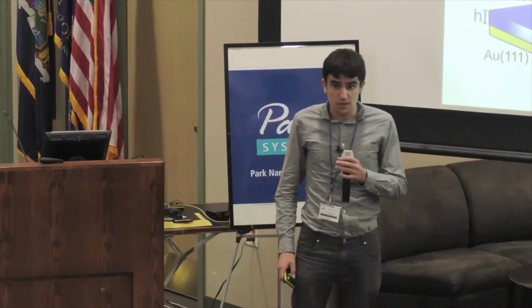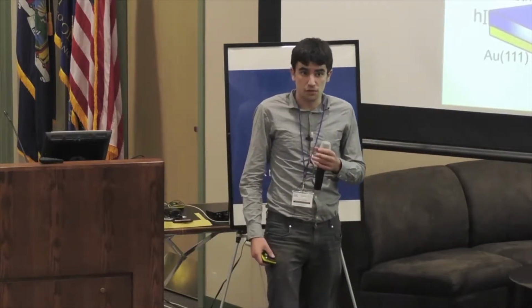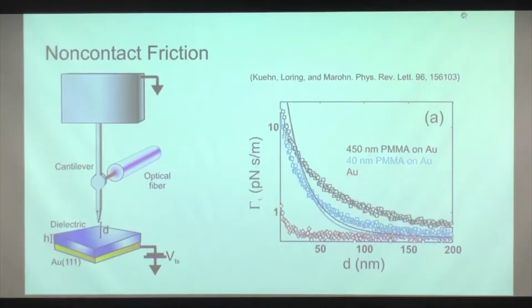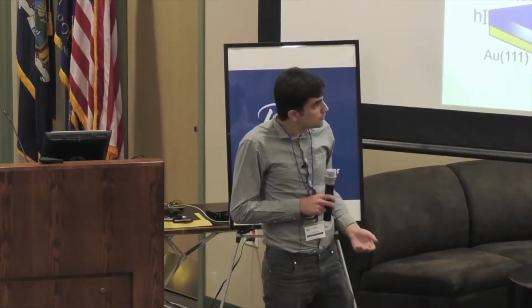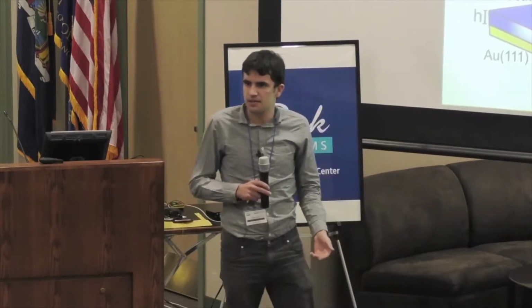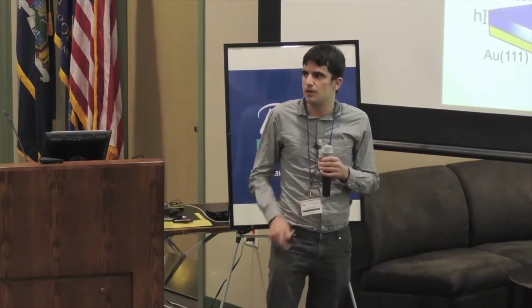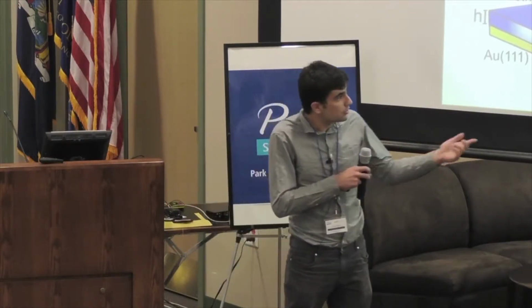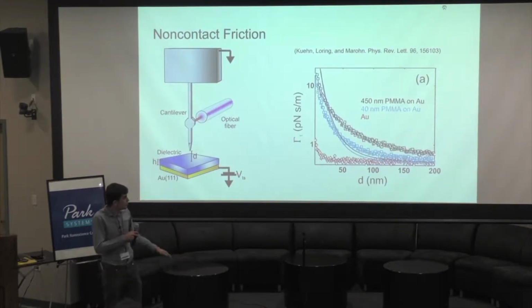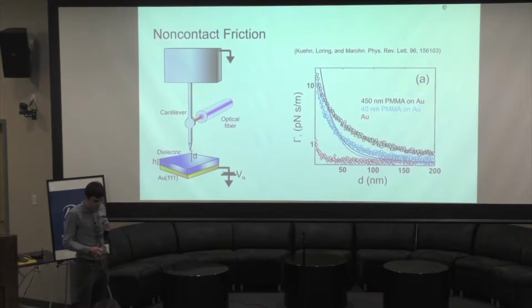So one particular form of friction that's of interest to ultrasensitive force microscopy, including magnetic resonance force microscopy, is what's called non-contact friction. It turns out that when you very closely approach the tip of a cantilever to a surface, the quality factor dramatically drops off with distance. And some excellent work in Dr. John Marohn's group indicated that this is due to dielectric fluctuations that introduce varying electric forces on the tip and damp its oscillation. On this plot, you can see a comparison of the non-contact friction above gold, a thin polymer layer, and a thick polymer layer, showing increasing non-contact friction, respectively.